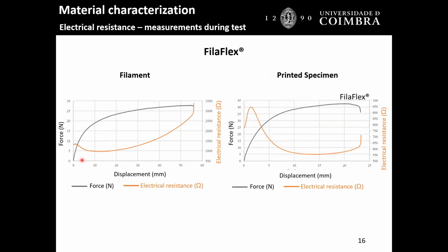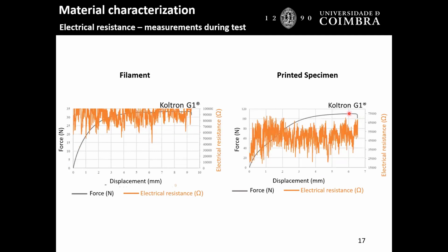During the test, what we saw is that with Filaflex, the filament, as you apply force, you almost maintain the electric resistance up to a value, then the electric resistance begins to increase, okay? In the printed specimen, you initially have an increase of the electric resistance, but afterwards you have a decrease. More or less the same results were obtained for Koltron G1, I say more or less, because the non-constant value measurement was absolutely catastrophic in Koltron G1. And we think this is related to the morphology of the reinforcements.